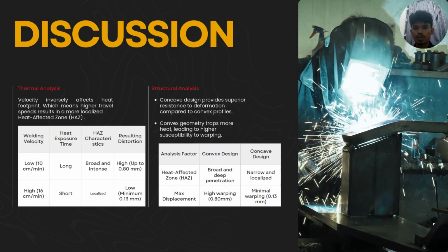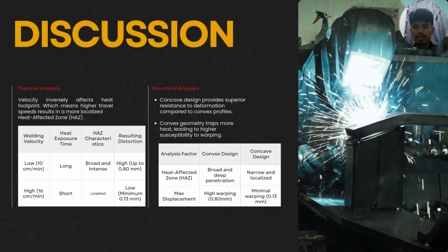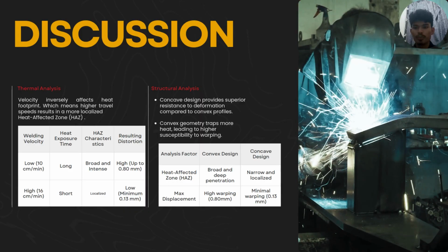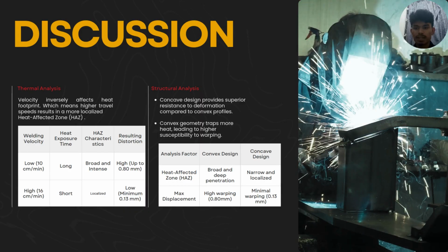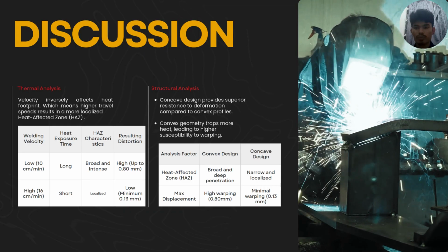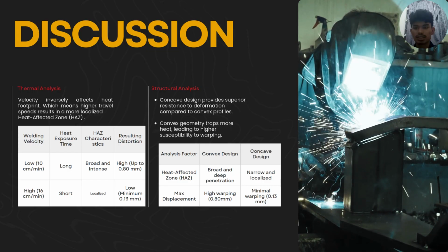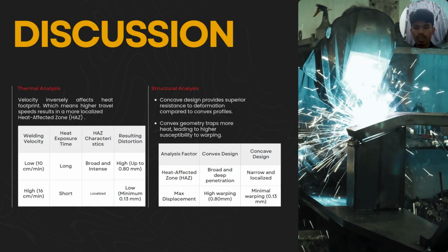For the structural analysis, the concave design provides superior resistance to deformation compared to convex profiles, and the convex geometries trap more heat, leading to higher susceptibility to warping.